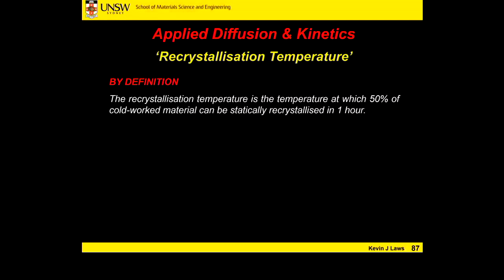So an industry manufacturer, cold rolling aluminium sheet. This sheet is very hardened, and fairly brittle because of the work we put into it. We want to recover 50% back to recrystallized grains with random orientation or texture. We would hold it at the recrystallization temperature for an hour to do that. So this is kind of not a laboratory but an industrial or experimental result.